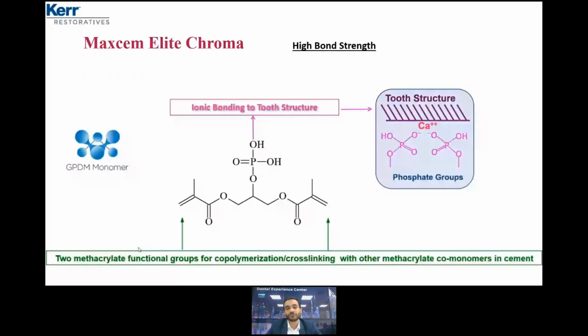And here I would like to consider two ways: the type of chemical reaction, the bonding strength to the tooth structure and also to the restoration. If I start with the bonding strength to the tooth structure, we have a specific adhesive monomer. On the left side, you can see a chemical component called GPDM, an adhesive monomer. It's a patent for Kerr. We use it in the whole OptiBond family, our adhesive family, and also in our dual cure cement.